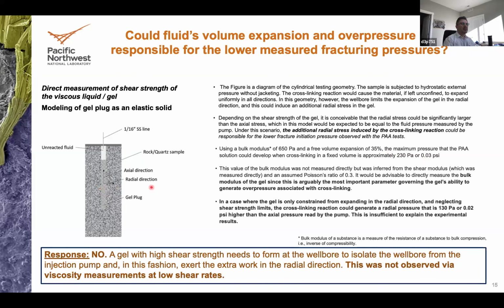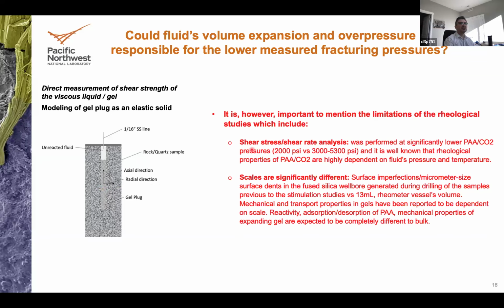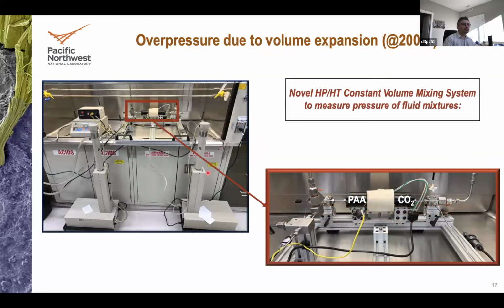So this rules out that there is an expanding shell. There are some limitations to the rheological properties that we measure, but nevertheless, we cannot justify that reduction in pressure associated to the volume expansion of the fluid. So we went to a next experiment because we wanted to measure the volume expansion, the stress associated to the volume expansion, in a larger vessel.